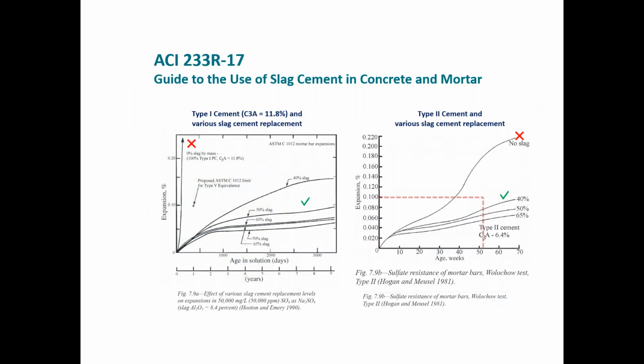So here's something out of ACI 233, and it's essentially showing the same thing we saw earlier. You look at where the red X's are. These are sulfate expansion bars with no slag cement, and then you look at varying replacement levels, and you see how you are decreasing the expansion over time. So that's pretty much all I wanted to show on that. Next slide.